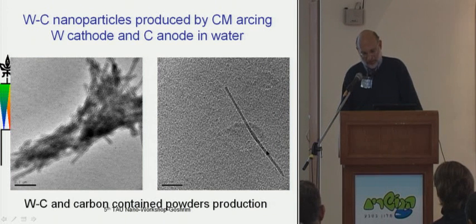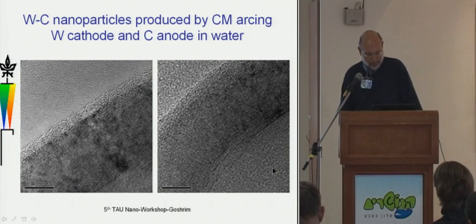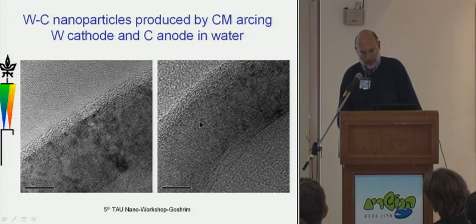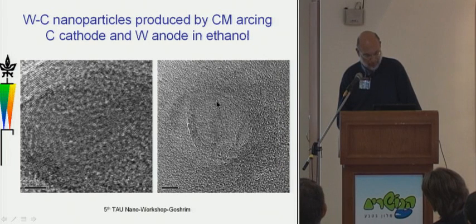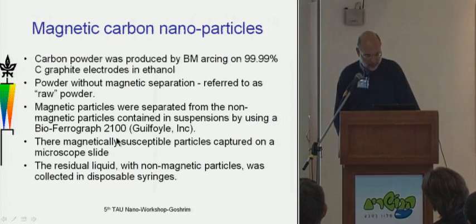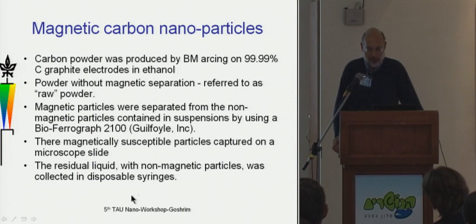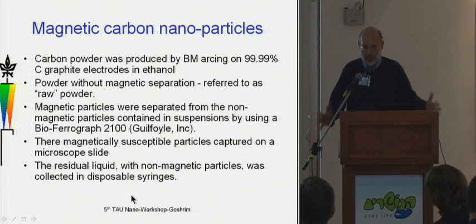Some of the particles you get are fibrous. Again, some kind of multi-wall nanofiber or nanotube, not quite sure. And now for perhaps the most interesting type of particle we produced. If we take carbon powder produced by breakdown mode arcing between graphite electrodes in ethanol, so basically the only material that's there is carbon.